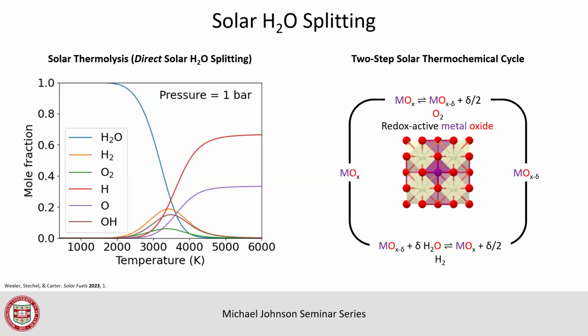What would happen if I cooled the system down? Once I cool the system down, it says, well, I only wanted to get rid of my oxygen because I was hot. Now I'm cold, I'd like my oxygen back. So if we present it with a source of oxygen, and that source is water, it is going to rip oxygen so dramatically out of water that we can very efficiently form hydrogen gas, and only hydrogen gas. It's not going to form some other thing like hydrogen atoms, which is problematic. We get hydrogen gas, and the oxygen that came from water makes our metal oxide again. Our rock is back to its original form.